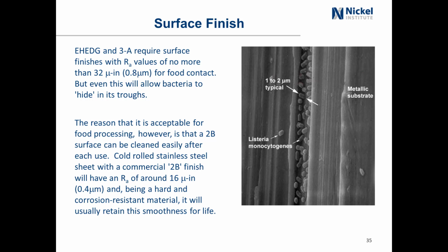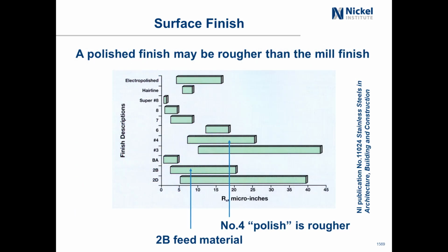Cold rolled stainless steel sheet with a commercial 2B finish would have an Ra value of around 16 microinch, about half of what's required by 3A and EHEDG. And being a hard and corrosion resistant material, it will usually retain this smoothness for life. Just to point out, a polished finish may be rougher than a mill finish.